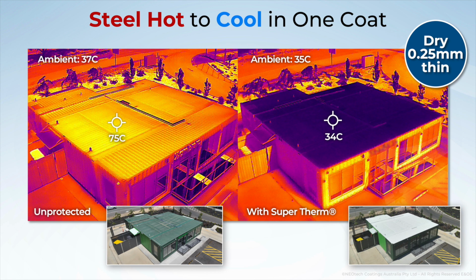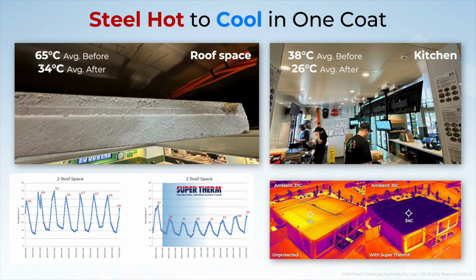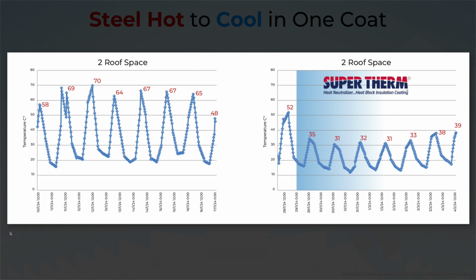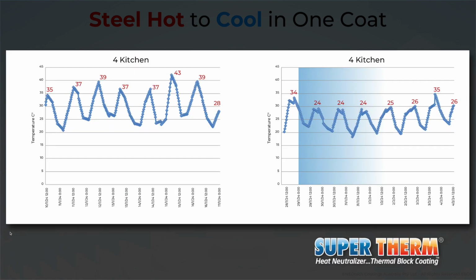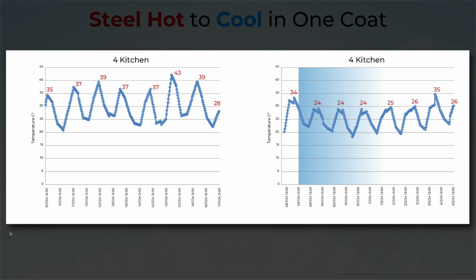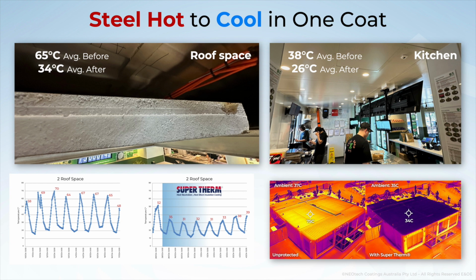We recently did a series of shipping container restaurants where within one coat we were able to reduce surface basically to ambient. And that was quite amazing, particularly for the staff inside the restaurant. Prior to that, they only had a small roof space, no insulation except for the 50mm PIR, and that was really hot, just as hot as the surface. So after we sprayed, we took the average from the roof space at 65 degrees down to 34 degrees average, which was well within ambient. And then also the kitchen staff went from 38 degrees, in fact there was a 40-degree temperature we recorded in there, down to a very manageable 26 degrees. So if you knock out the heat at the surface, it's not going to transfer, then you can just work within the ambient temperatures, which is primarily where your heater, your insulation, and your air conditioning can work as well.